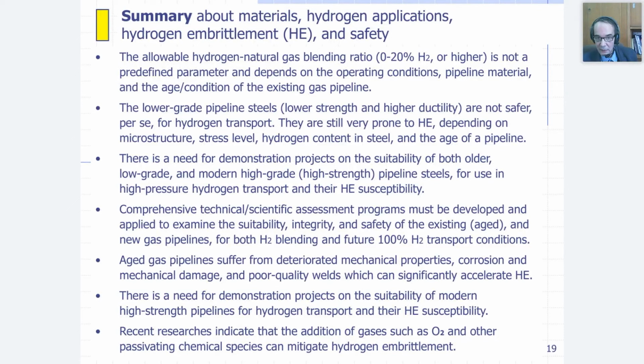The lower grade pipeline steels with lower strength and higher ductility, the older ones, are not safer per se for hydrogen transportation in comparison to higher strength modern pipeline steel, since they are still very prone to hydrogen embrittlement depending on microstructure and other factors. So there is a need for a demonstration project on suitability of both older, low-grade and modern high-grade pipeline steel for use in high-pressure hydrogen transport for long-term with a very high safety in order to provide the reliable exploitation of hydrogen pipelines. And also it is important to investigate the hydrogen embrittlement susceptibility of the old steels in older pipelines.